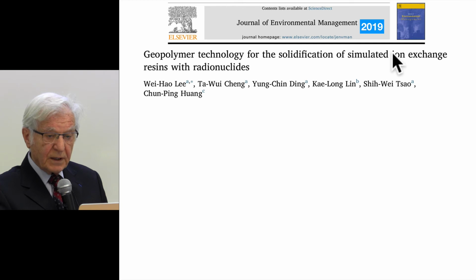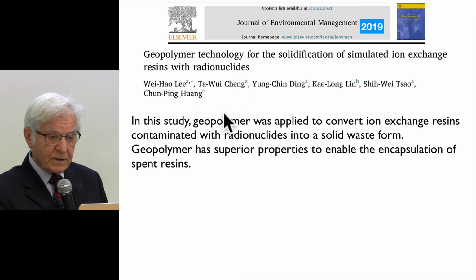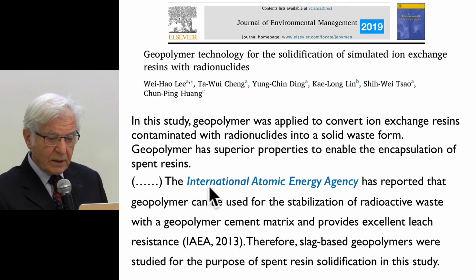Geopolymer technology for the solidification in simulated ion exchange resin with radionuclides. This is from Taiwan. In this study, geopolymer was applied to convert ion exchange resins contaminated with radionuclides into a solid waste form. Geopolymer has superior properties to enable the encapsulation of spent resins. The International Atomic Energy Agency, that is in Wien, has reported that geopolymer can be used for the stabilization of radioactive waste with a geopolymer cement matrix and provides excellent leach resistance. Therefore, slag-based geopolymer was studied for the purpose of spent resin solidification in this study.